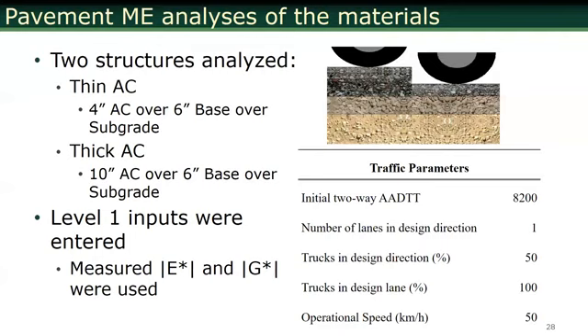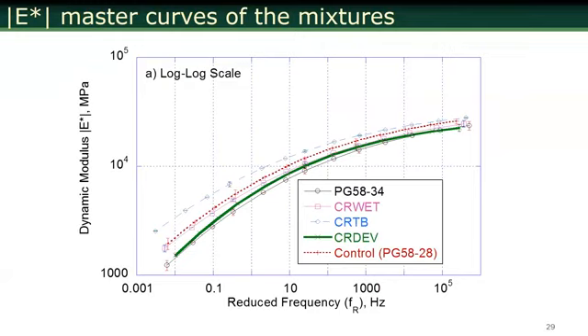Our thin structure was a 4-inch AC over a 6-inch base, and our thick structure was a 10-inch AC over a 6-inch base. We used level 1 inputs for all E star and G star. We measured all these for all 5 different combinations of materials. We used the same traffic level. And these are the dynamic modulus master curves of all these mixtures.